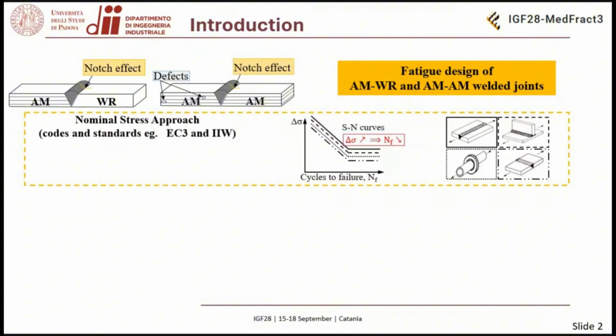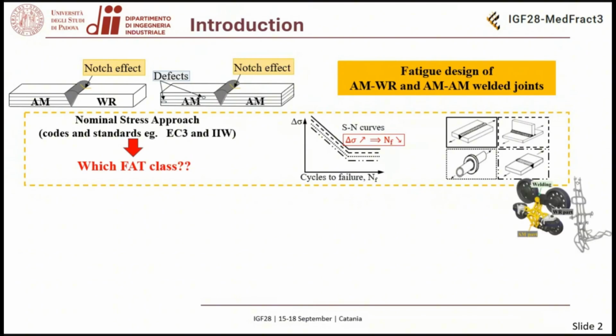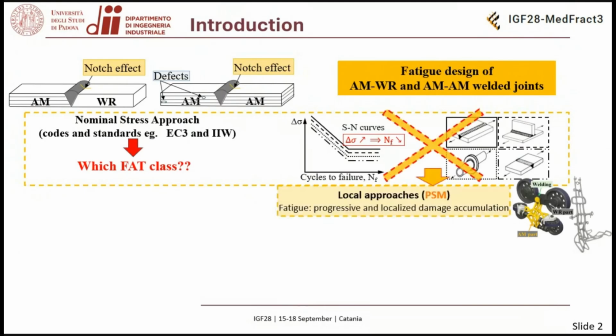In addition, when we talk about traditionally manufactured welded joints, we have standards, for example, the Eurocode 3, which provide the specific design curve, each one for a specific joint geometry and specific loading condition. However, if we talk about joints with the AM part, at the moment, there are no standards. In addition, we refer to complex joint geometry and complex loading condition, and that's why a local approach is needed.